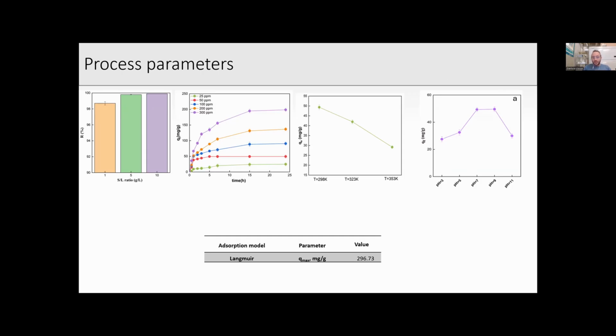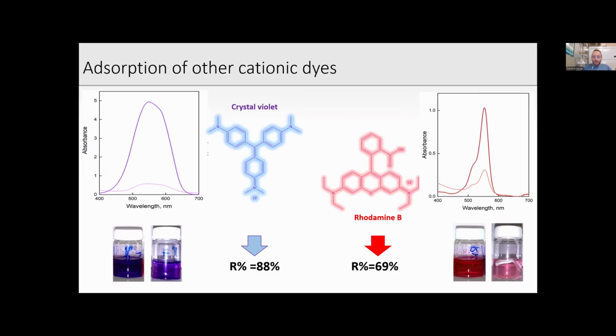And in all these cases, the adsorption performance of this new material to remove organic dye from wastewater is proved, with a maximum adsorption capacity proved by the Langmuir model equal to about 300 milligram per gram. Even in this case, this novel material was applied not only to remove methylene blue from water solution, but even other cationic dyes such as crystal violet and rhodamine B. In this case, the membrane is able to remove about 90% and about 70% of these two cationic dyes from water solution, proving the ability to be used for different classes of contaminants.